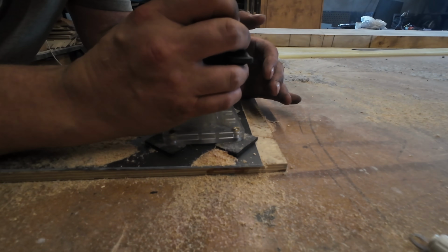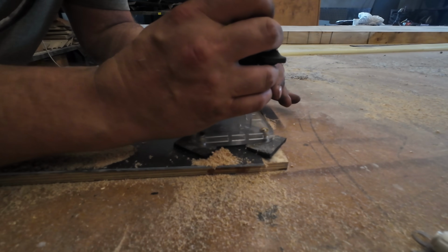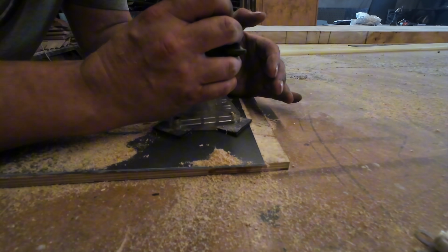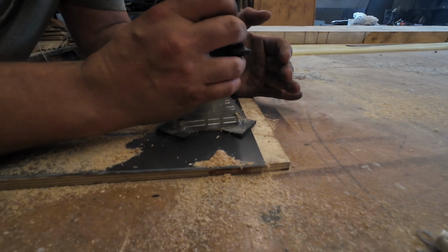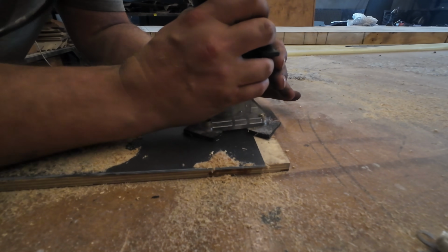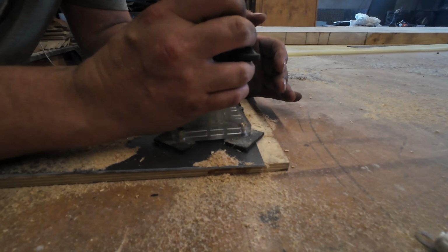We tested everything separately on plywood first. In my opinion, the result is excellent. The router cut passes 2.5 millimeters from the edge of the template, the corner radiuses are clean and everything looks straight and nice.